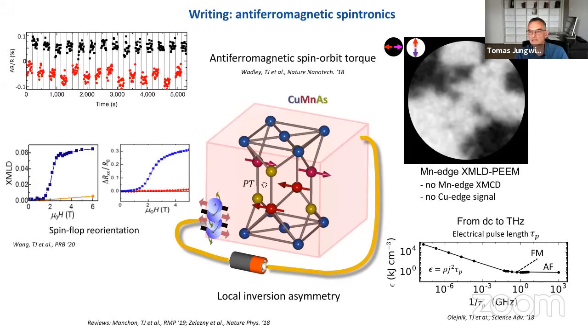length. This is an experimental image here, which shows the energy required to switch an antiferromagnet, again, the copper manganese arsenide, as a function of the inverse pulse length. And what you see is that in antiferromagnet, you can in fact extend the operation of your device all the way to the terahertz pulses. That means electrical currents, pulses of the length of 1 picosecond. So it seems that one of the expected advantages of antiferromagnets compared to ferromagnets, that means their speed, could indeed be realized in these devices.